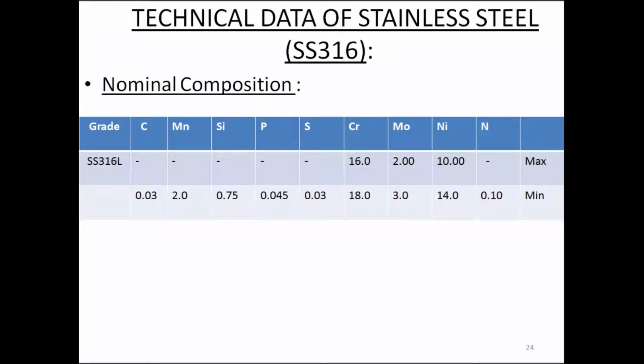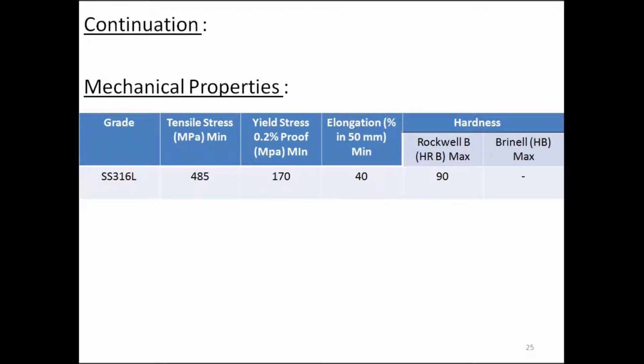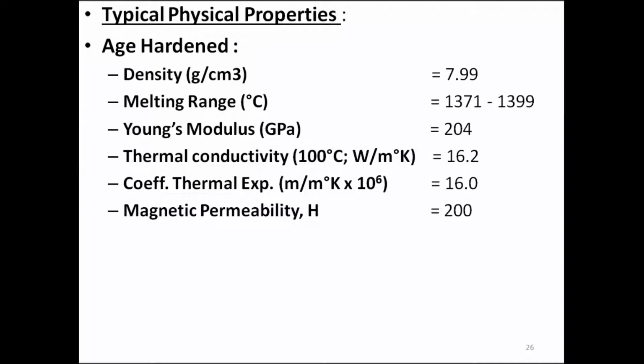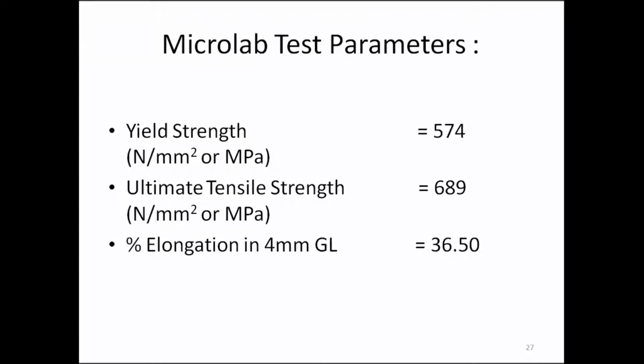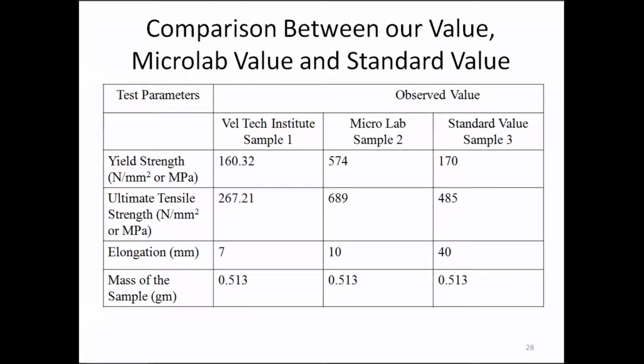The technical data of the stainless steel SS316L. The nominal composition. Here we get each and every material involved in the SS316L. These are the mechanical properties, which are universal standard properties for tensile strength, yield strength, elongation, hardness for SS316L, and here are the physical properties. This is the Microlab test parameters, where we get yield strength equal to 574 megapascal and ultimate tensile strength equal to 689 megapascal, and percentage elongation of 4 gauge length equal to 36.50%. Here we compared the values taken from Vel Tech Institute, Microlab value and standard value.